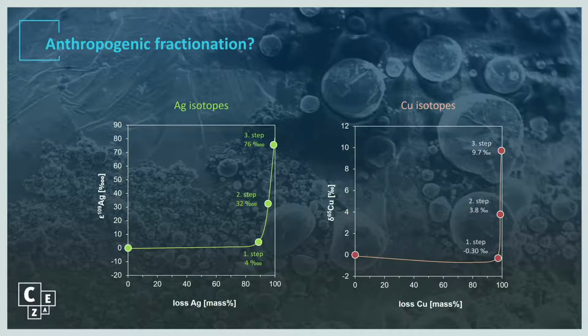You see here, the more silver we remove from the gold that we cemented, the larger the fractionation. When you have a removal of, let's say, 95% or more, you have a very, very large fractionation. This is the same with the copper isotopes.